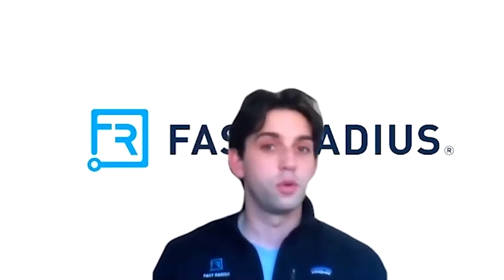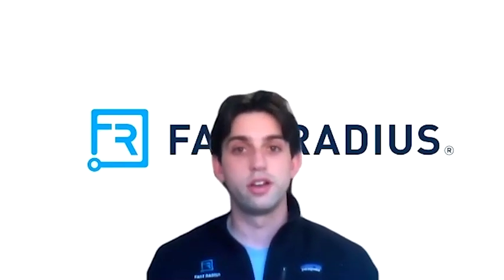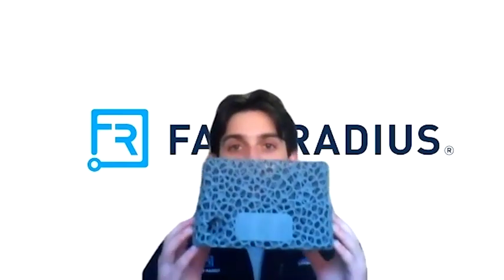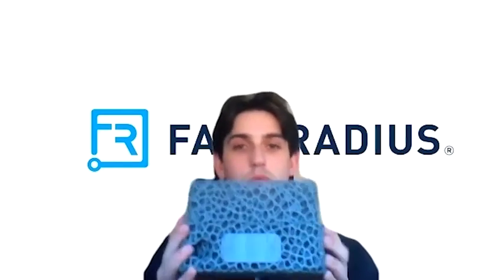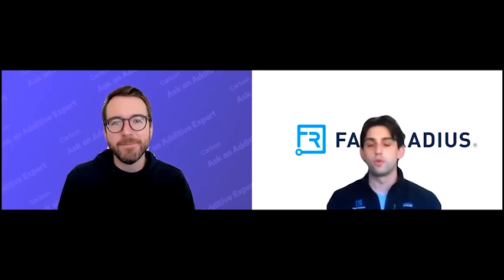The really cool thing about lattices with elastomerics is that you can blend lattices together and create different responses on different parts of a single solid volume. You can control where the thickness is increasing and where it's decreasing — a thicker lattice is going to have a stiffer response than a thinner lattice. You can actually target where those thick areas are and where those thin areas are to improve the performance of your part even further. We designed a neck pillow using the SIL material on the M2 machine with a thicker base and a very thin, squishy top half — a great example of how variable thickness lattices can improve the performance of an already great part.